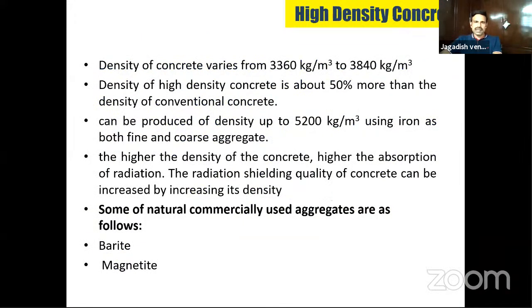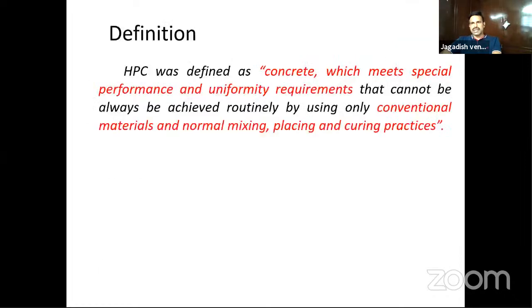And there is a high density concrete. This concrete, we use it for radiation shielding. Some of the aggregates we use for this high density concrete are barite or magnetite. The density goes up to 3,360. Some concretes using iron, you can go up to 5,200 kg.